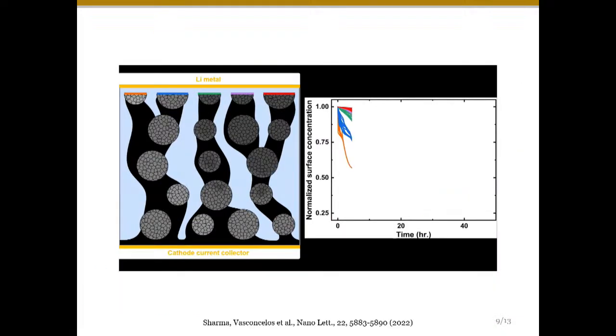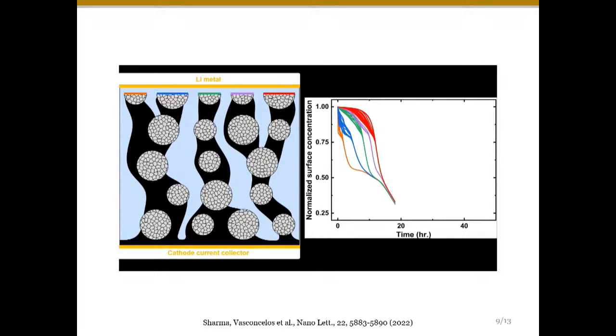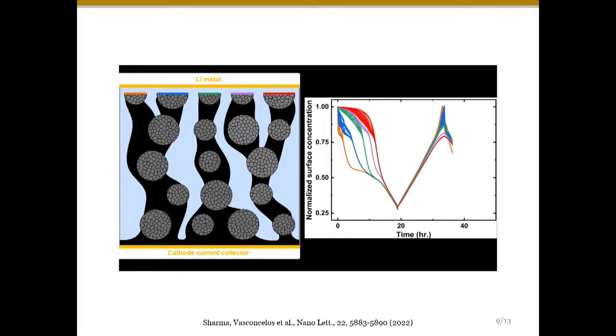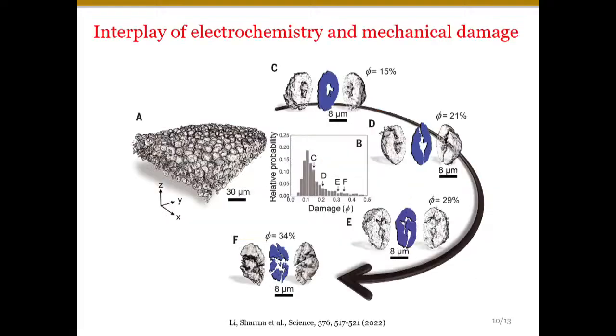This is our lithium concentration profile. The vertical axis is the idealized concentration for topmost particles, and the horizontal axis is time. During the first charging process, there is a lot of variation of concentration among particles. During discharge, it converges, and then again there is a relatively minor degree of asynchronous behavior.